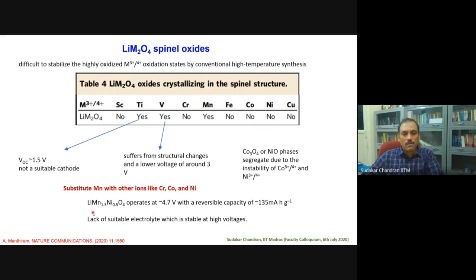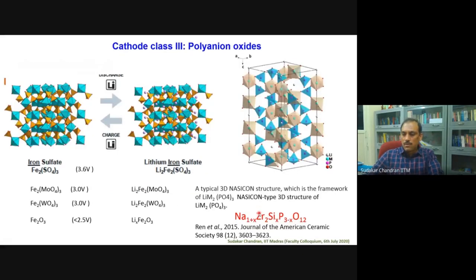There were other compounds where they substituted two different elements and tried. One very promising compound is if you substitute 0.5 nickel in the place of manganese, that is LiMn1.5Ni0.5O4. This operates at much higher voltage than LiMn2O4, around 4.7 volt, with the capacity, which means you can increase the energy density. But then the problem is you don't have a suitable electrolyte. The electrolyte will undergo redox reactions if you go beyond a certain voltage. So there are issues with that too.